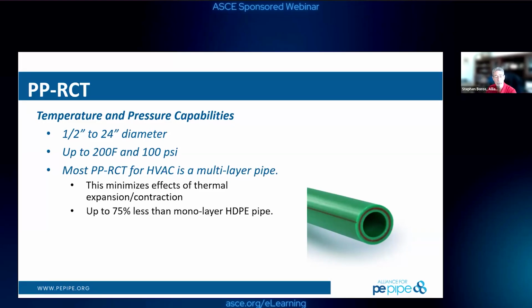And so that glass fiber layer, its main purpose is not to add more hoop strength to give it more pressure rating capability. It's really to minimize the thermal contraction and expansion of the pipe. So it gives about 1/10, I think, of the amount of thermal expansion contraction that you might see in a non-reinforced polypropylene pipe. That really helps when you're designing these mechanical systems inside these large data centers, so you don't get any of those large temperature movements. You can compensate for that, but this material means you don't have to.